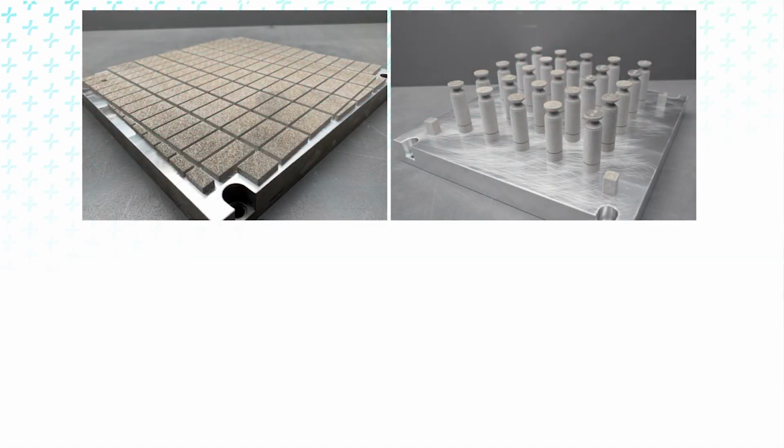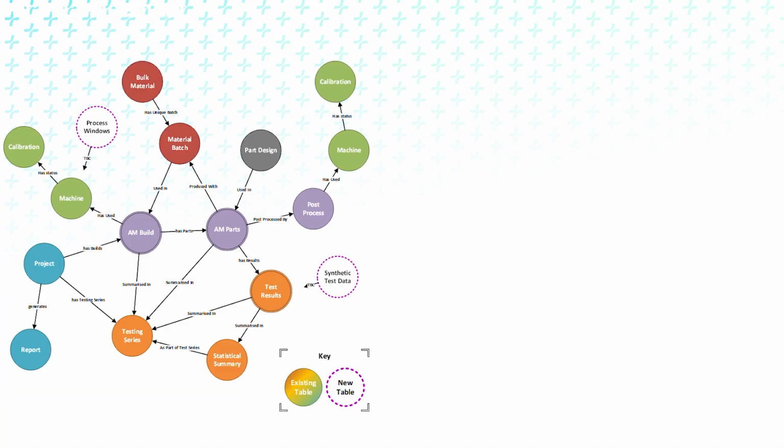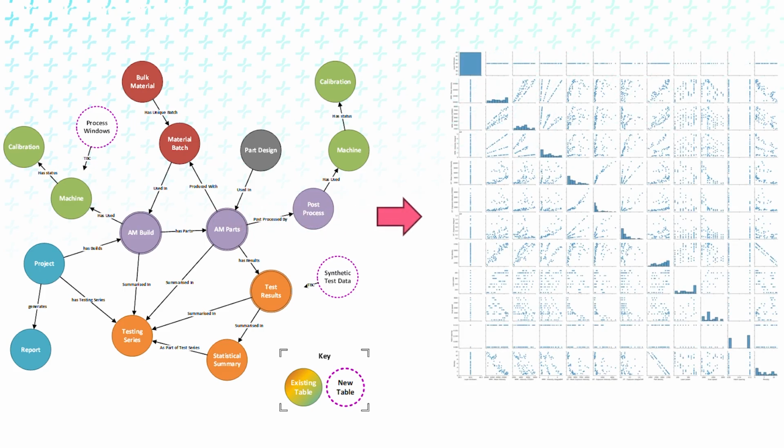Our additive manufacturing team focused on running a campaign of builds through this project, which allowed us to identify correlations between in-process monitoring data and defect presence in those parts, very specifically porosity. And we identified some correlation between those two that allow us to feed that information into an AI tool, which can process that large population of data to eventually output a part quality statistic.